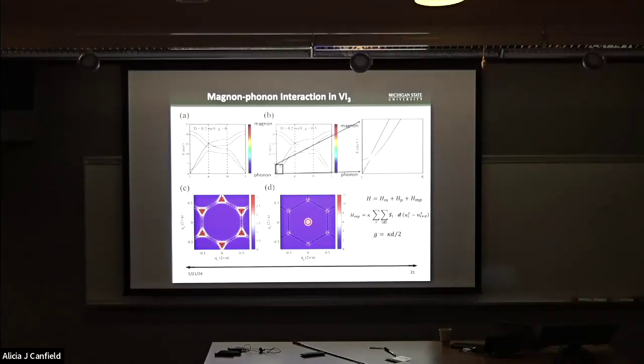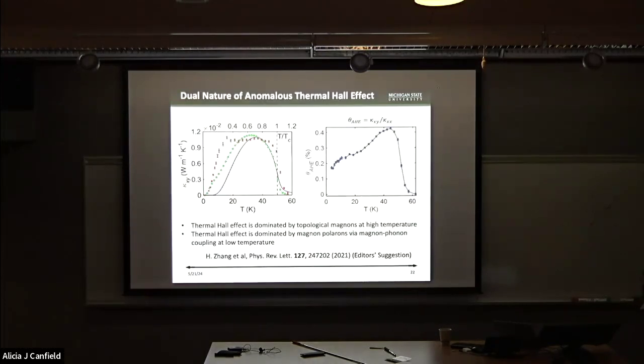It's going to form a new particle, the so-called magnon polaron. And along this anti-crossing point, these bands would have very large Berry curvature. And the Berry curvature is so large, it's even larger than the Berry curvature induced by the DM interaction. And since this anti-crossing occurs at low energy, right? So of course they are going to contribute to the low temperature thermal Hall conductivity. And this is exactly what we see in the calculated results.